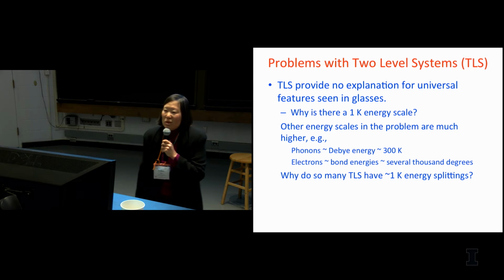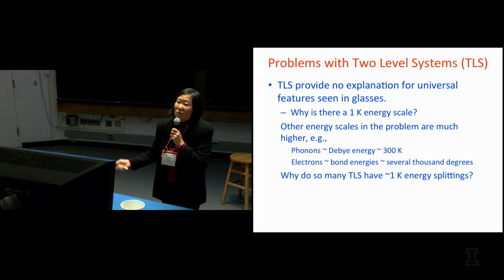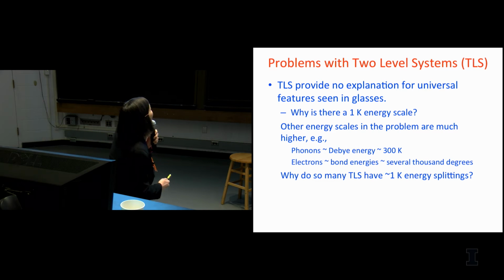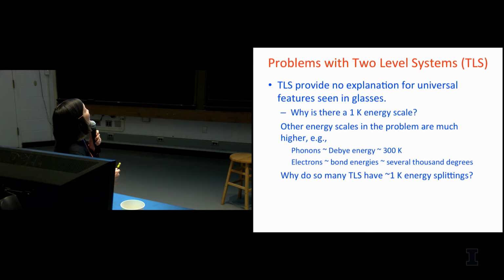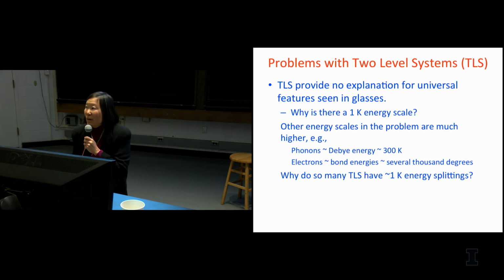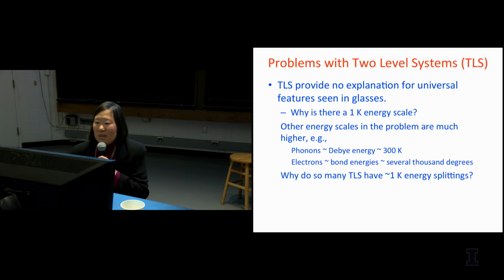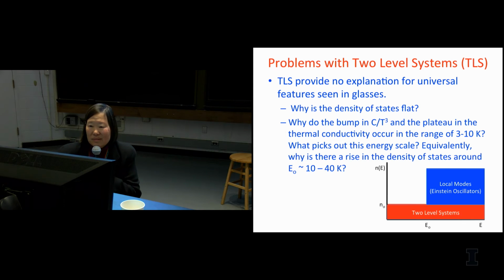Another point was that there was no explanation for the universal features seen in glasses. So here are some of the questions that occurred to me. Why is there a 1 Kelvin energy scale? If you look at all the other energy scales in the problem, they're much higher. Phonons have a Debye energy of order 300 Kelvin. Electrons have bond energies that are several thousand degrees. Why do you have all these two-level systems with their splittings of order 1 Kelvin?